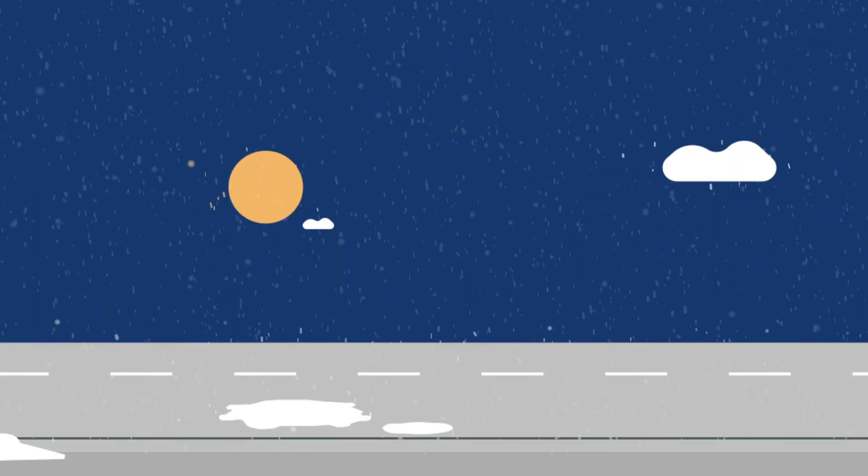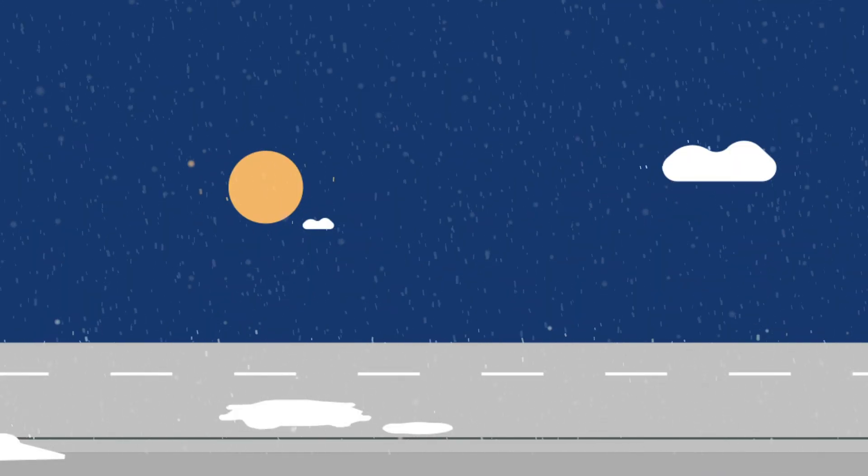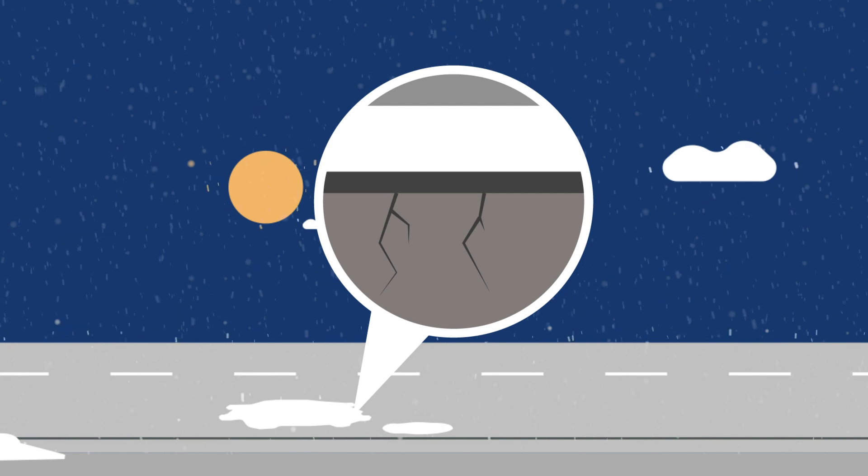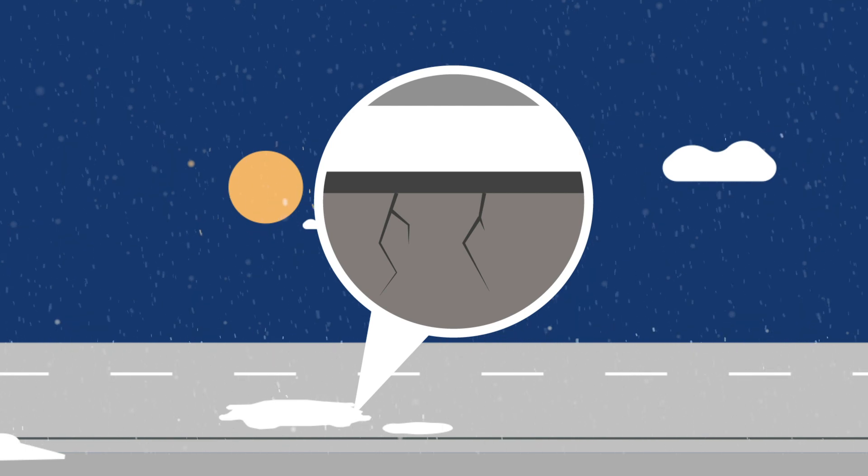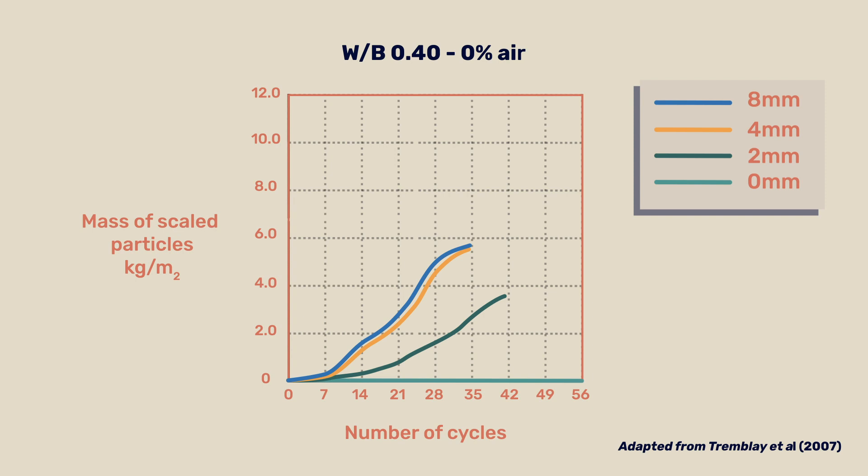In such cases, the damage is known to increase when the depth of the freezing water increases. As shown in this graph, the mass loss is greatest for the thickest layer, zero without the liquid layer, and intermediate otherwise.